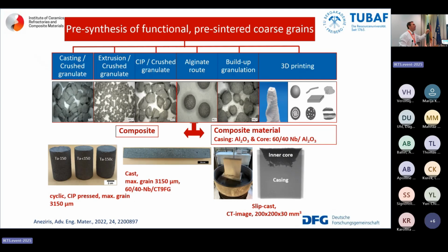Let's make big grains as we have it in the refractory thinking and pre-sinter them. Why? I want to take out the shrinkage. I want to have a pre-sintered product, coarse-grained metal ceramic. And if I do this, I can make big components. I can make big electrodes. I can integrate these electrodes in pure alumina systems. Thilo Tsinat is going to speak Tuesday, Wednesday, I don't remember now.